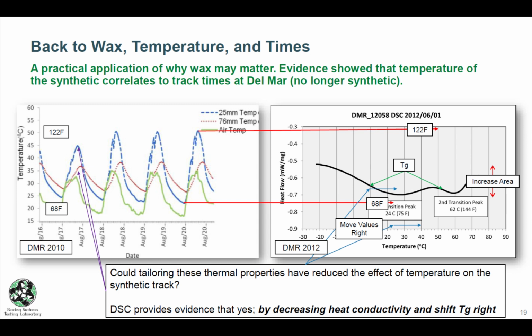The DSC provides evidence that yeah, we can measure these changes in the heat conductivity of the surface. We can measure the thermal properties, and when these transitions in temperatures are going to occur, there is the possibility that you can apply the method to determine what temperature ranges we are going to be dealing with for this wax, and should we use this wax maybe in Kentucky versus California versus New York, and we're able to provide insight on that.